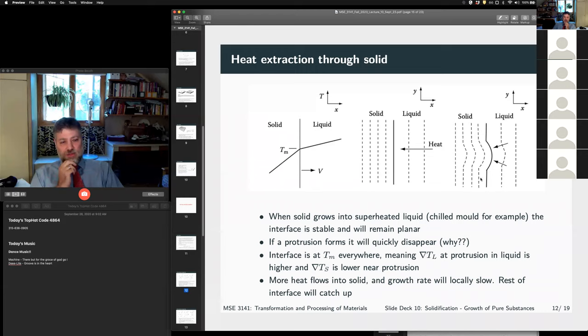And if we form a little bump like this, right, what's that going to mean? Everywhere on this interface is still at the melting temperature, right? And out here, this temperature is constant, and out here, this temperature is constant. So we have a longer distance for our temperature change in our solid, which means that this gradient becomes more shallow, and we have a shorter distance in our liquid because of this bump. So that means that this gradient becomes steeper, right? And if we're conducting heat this way and our gradient is shallower, that means we're going to conduct less heat through this bump, right?